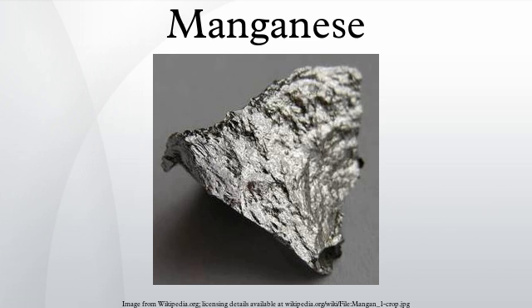Small amounts of manganese improve the workability of steel at high temperatures, because it forms a high-melting sulfide and therefore prevents the formation of a liquid iron sulfide at the grain boundaries. If the manganese content reaches 4%, the embrittlement of the steel becomes a dominant feature. The embrittlement decreases at higher manganese concentrations and reaches an acceptable level at 8%. Steel containing 8 to 15% of manganese can have a high tensile strength of up to 863 MPa. Steel with 12% manganese was used for British steel helmets. This steel composition was discovered in 1882 by Robert Hadfield and is still known as Hadfield steel.